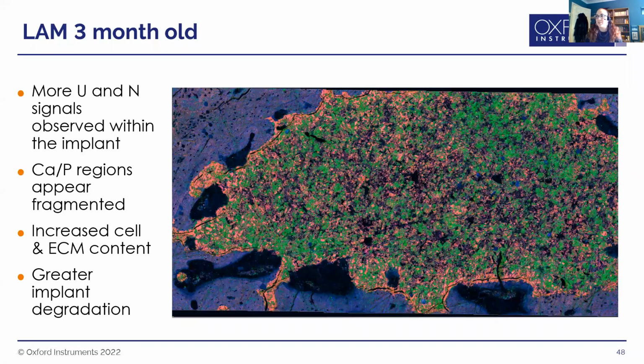And if we go to the EDS maps, immediately you can see there's a load of green material in the implant, the kind of peach material, which is the implant itself. A combination of the calcium and phosphorus signals is much more broken up and is in various bits all around the place. And you can see really big accumulations of nitrogen in here as well. So we don't quite know what's going on in those regions.